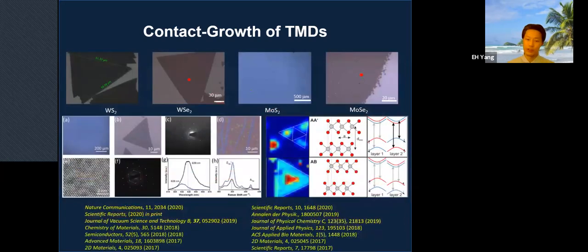Using this method, we have published several articles in the past couple of years on monolayer growth, heterostructure growth, and stability issues. I mentioned air stability. We demonstrated air stability of tungsten disulfide directly grown on graphene, and we published it in Advanced Materials, a cover article. We also worked on homobilayer growth. Homobilayer means you have two of the same types, like WS2, WS2, but as bilayers. Basically you can control all these directions, and we use that for electronics applications. Of course, the electronics experiments were done at the collaborators' lab, not by us.